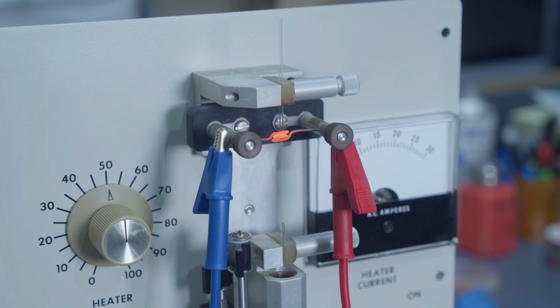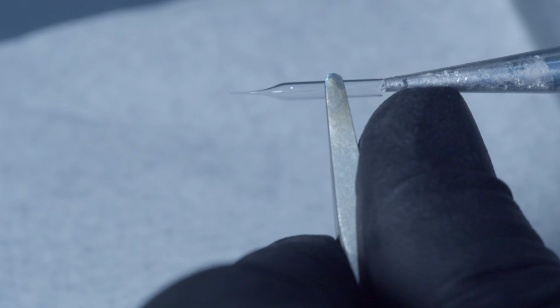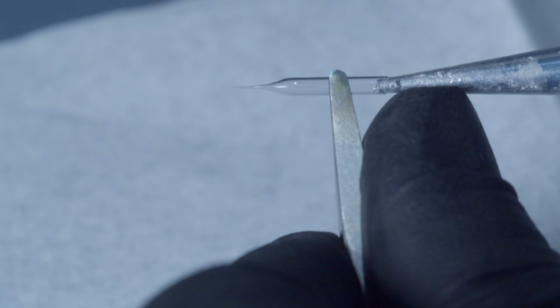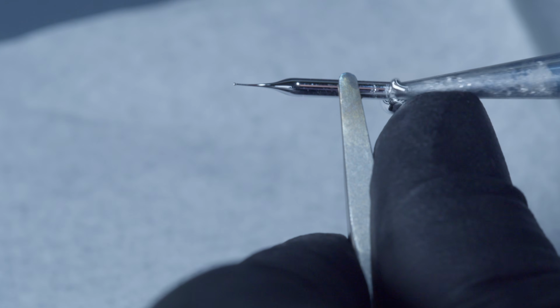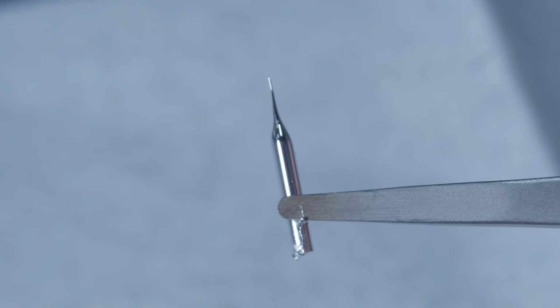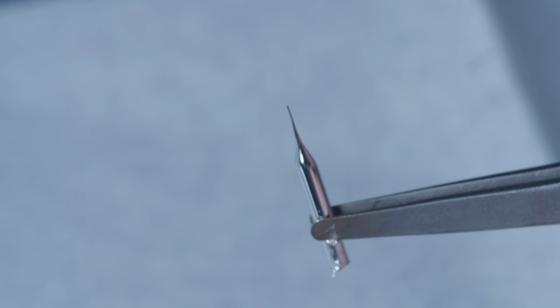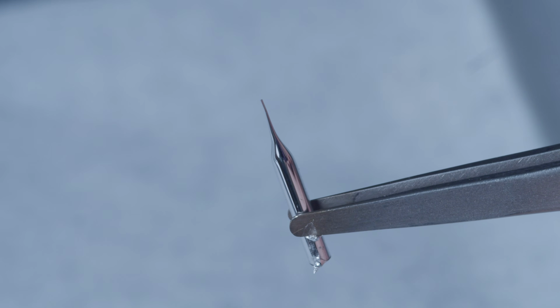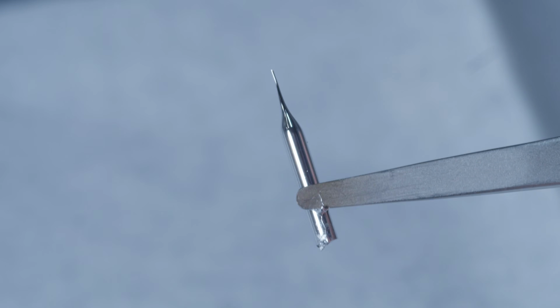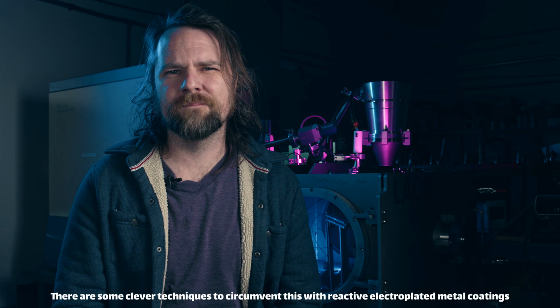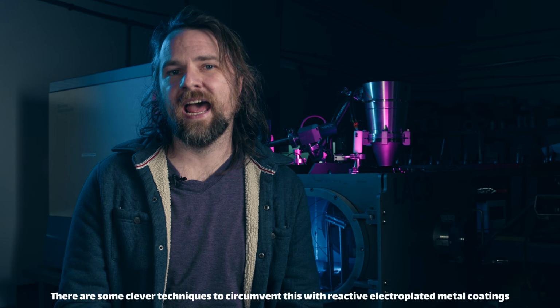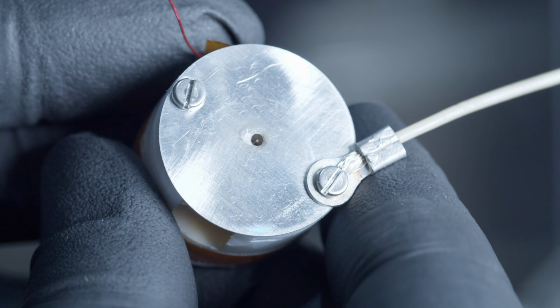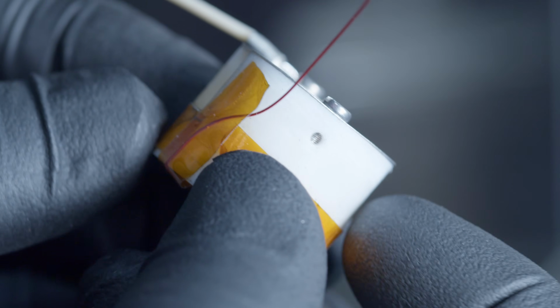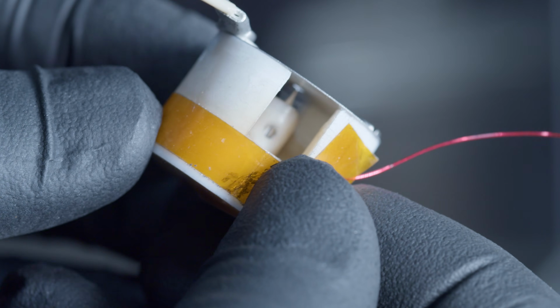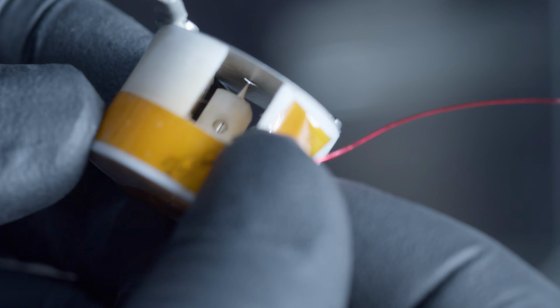Once pulled, the capillary is cut down to size and filled with gallium. You can actually pull tips that are crazy small, like only a micron or two wide. These are used in electrophysiology all the time as patch pipettes. But at some point, the pressure required to fill it with gallium gets so high that you just explode the capillary. So there's a practical limit to how small you can make it. A nice feature about these glass capillaries is that they're entirely insulating, except for where the gallium pokes out the top. This should, in theory, help prevent arcs and accidental shorts.